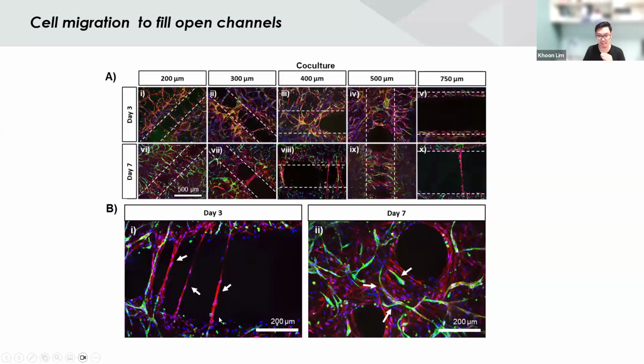What we also found that is interesting is that all of these red colored cells are actually mesenchymal stromal cells. The green here are the endothelial cells. So we see a lot of single MSC bridges. So at day 3, you get these single bridges. So the MSCs are the ones that are forming this pathway or this bridge for the endothelial cells to then come to migrate on them.